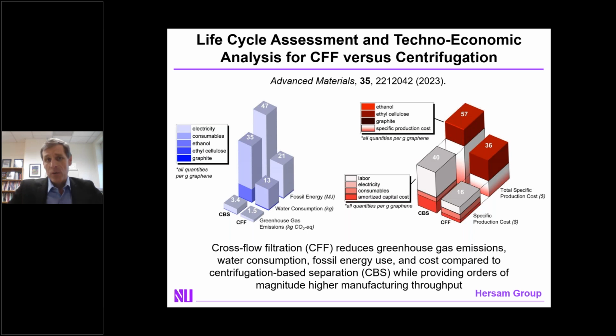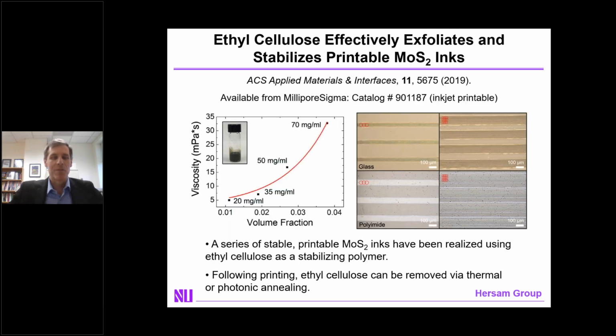This use of cross-flow filtration compared to centrifugation also gives you substantial advantages in greenhouse gas emissions, water consumption, fossil energy use, and costs compared to conventional batch-based centrifugation, while concurrently achieving orders of magnitude higher manufacturing throughput. The bottom line is that we can produce huge quantities of these inks. The next step is to actually put them into a printer and see if they print effectively. What I'm going to show you now is printable molybdenum disulfide inks.